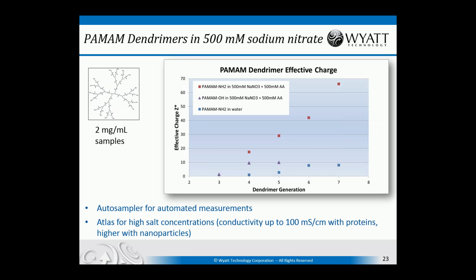So here's an example of a measurement of some dendrimers in very high ionic strength solution, 500 millimolar sodium nitrate. We can see the measurements of the effective charge of these dendrimers through the dendrimer generations from 3, 4, 5, all the way up to 7. And it's a function of the chemistry of the system, so different amounts of acetic acid incorporated into the dendrimer give it a different charge, of course. And these are very robust and accurate measurements. You can see that there's very little noise in these measurements.